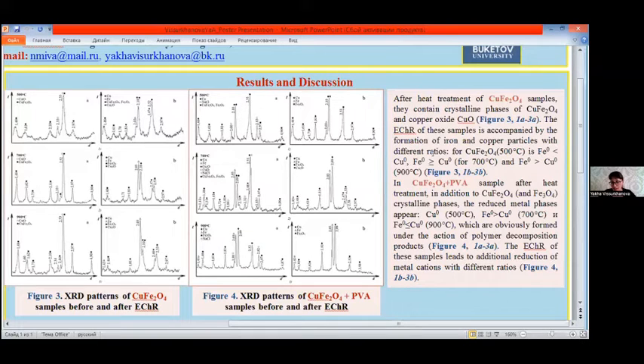ratios are formed. Let's look now at figure 4, namely X-ray patterns of copper ferrite samples prepared with the addition of polyvinyl alcohol. According to figure 4, after heat treatment, there are the crystalline phases of copper ferrite, iron oxide, as well as reduced copper and iron with different ratios. The electrochemical reduction of these samples leads to additional reduction of metal cations.